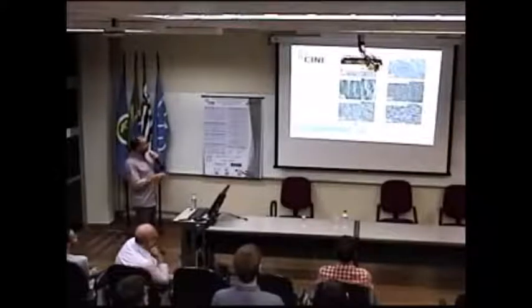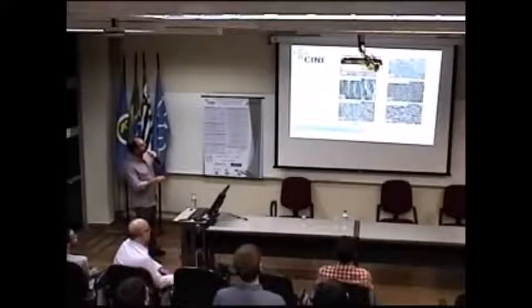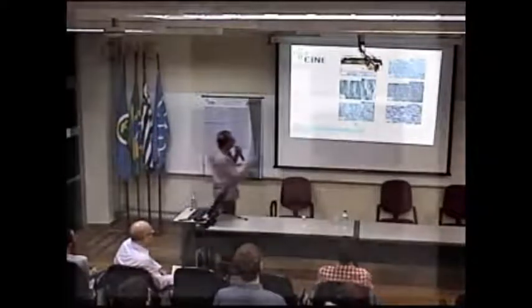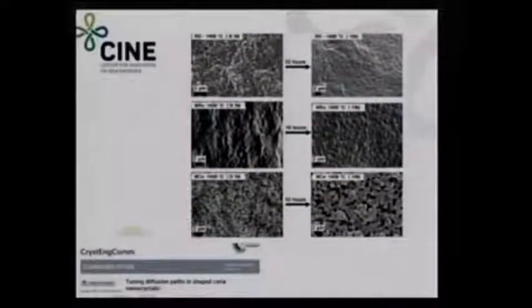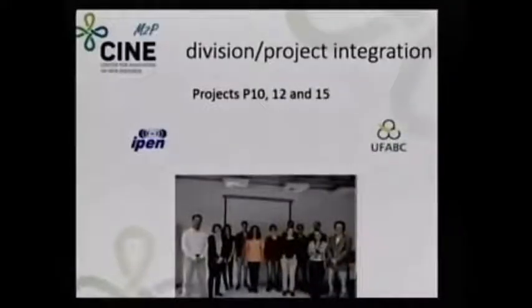So this is what we've been working on at this point. Those are the resulting microstructures. This is nanorods at 0.1 hour, very quick at 1,400 C. We sinter those particles, and they already get very dense. At 10 hours, you have a beautiful microstructure, very similar to the nanoparticles with random shape. But the nanocubes, no. This is 0.1 hour. In 10 hours, you have a rather porous structure, which can be very interesting, like I said, for catalysis. And those are projects that are shared between different projects of our divisions. Those are the high temperature people.